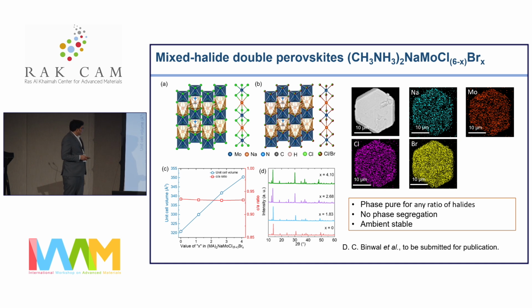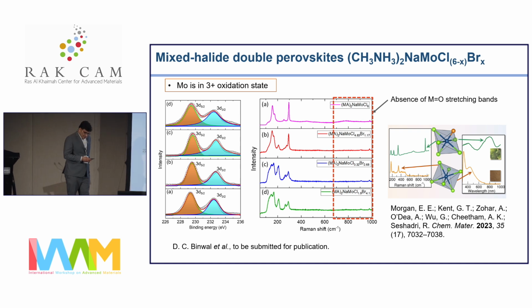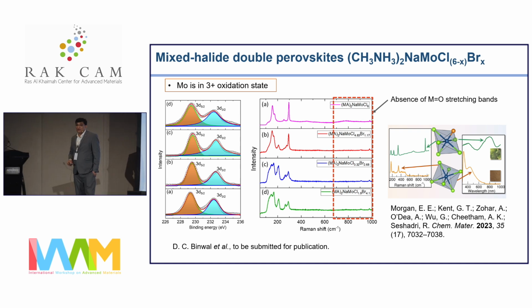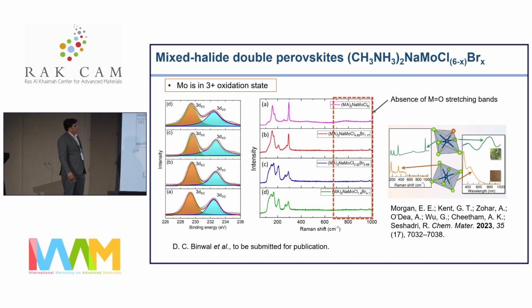But interestingly, we don't know the reason, the c by a ratio remains constant. It doesn't change. And we also looked at another structure which has a one-dimensional structure. There also the c by a ratio is similar, which is close to 0.95. So it seems to be constant across all compositions. So what we looked at here is the magnetic measurement on the series of compounds.